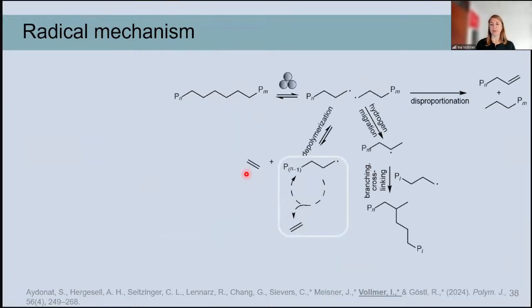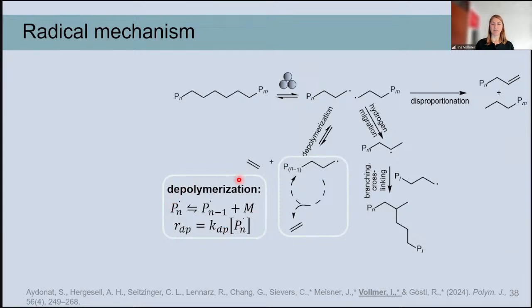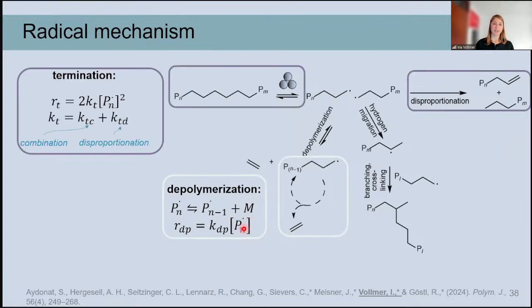So if we want to promote the depolymerization, we can apply a kinetic trick that is also very well known from radical polymerization. The trick is that for the depolymerization, the rate depends on the radical concentration to the power of 1, while for the termination, it depends on the radical concentration to the power of 2. So if we decrease the radical concentration, we suppress the termination much more than the depolymerization, and thereby we can promote the depolymerization over the termination. As I explained before, we think that with our catalyst, we can stabilize the radicals for a while. This decreases the radical concentration in the system and thereby promotes the depolymerization and suppresses the termination reactions.